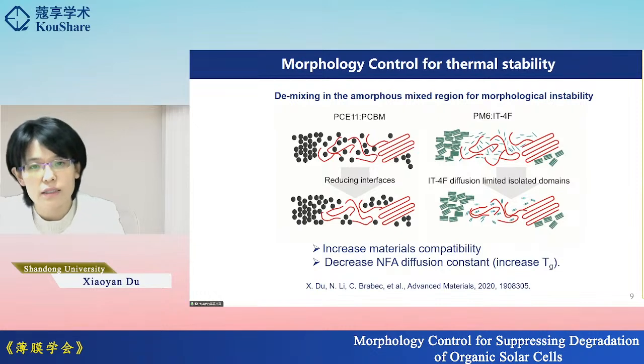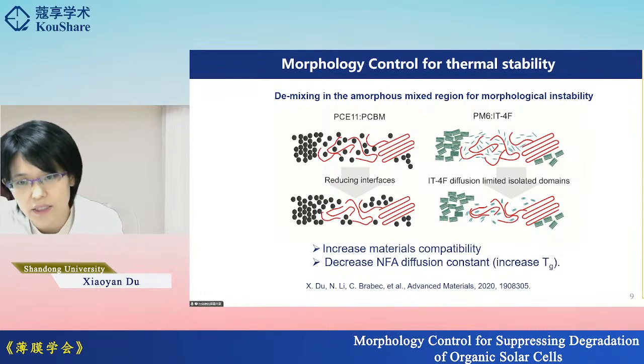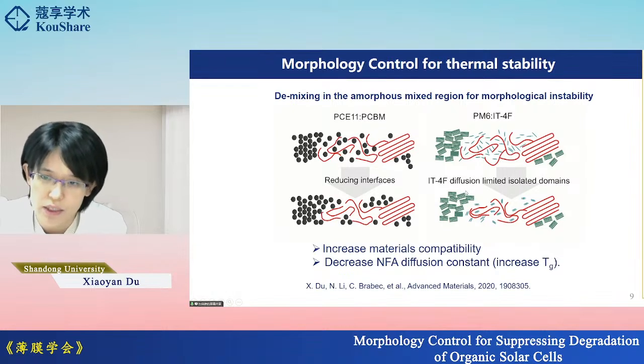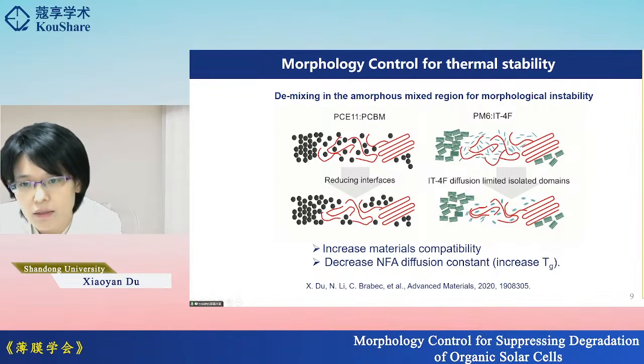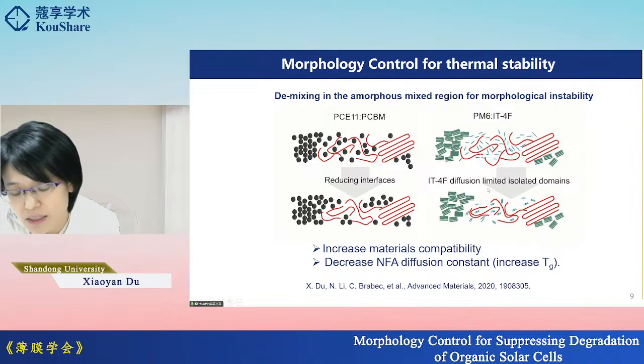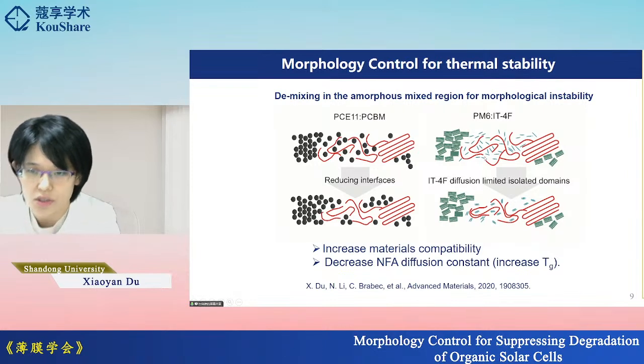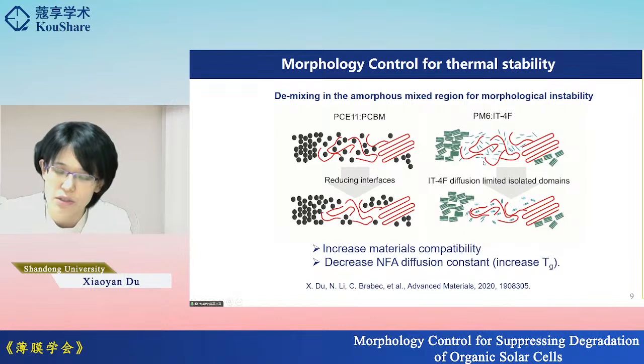Okay, now in the next slides, I will mainly talk about the morphology control for the stability of the solar cells. Previously, in this work, we discussed the demixing in the mixed amorphous regions in these fullerene-based and non-fullerene-based organic solar cells. And we speculate, or we propose, that the demixing in the amorphous region, and especially the diffusion-limited diffusion of the non-fullerene acceptors, is one of the degradation origins for this morphological instability.